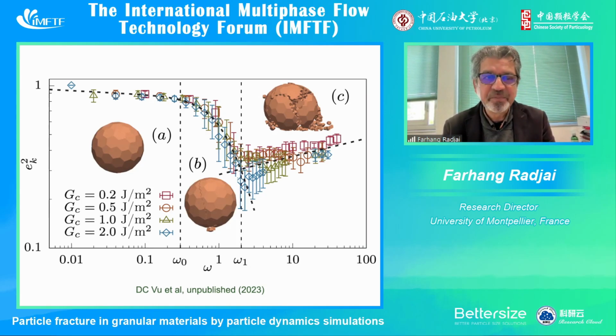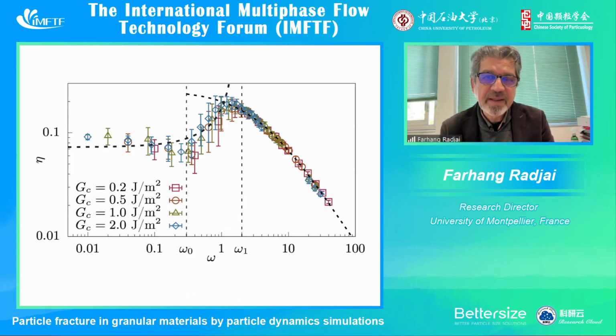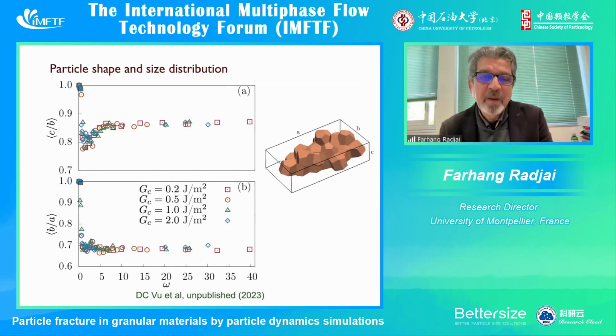and also fragmentation. So let me also add here that we studied recently the shapes of the fragments generated using a bounding box. So if you use the fragments and the bounding box with three dimensions A, B, and C, you can characterize either C over B or B over A as a function of omega, again, this parameter. And we see that C over B is generally very close to 1, nearly 0.9. This is also what is found in some experiments. But B over A, which is somehow the elongation of the particle, tends to a value which is about 0.7.